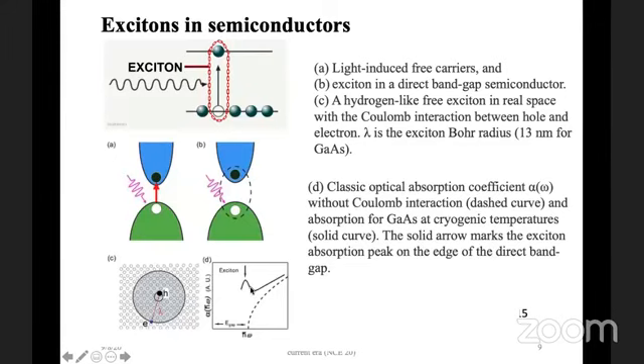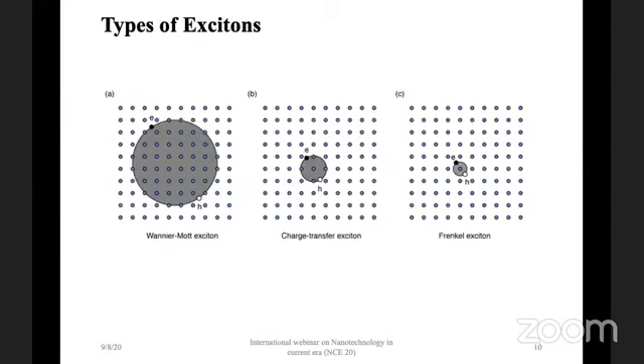Sometimes this one is seen very strongly in the PL spectra as well at low temperature. Mind you, we can see only this at low temperature. At high temperature, we don't. At room temperature, we don't see this exciton because a lot of phonons come into play. If we mask the phonon somehow, then we are able to see the exciton peak, and that we can only do if we do a low temperature absorption or low temperature photoluminescence.